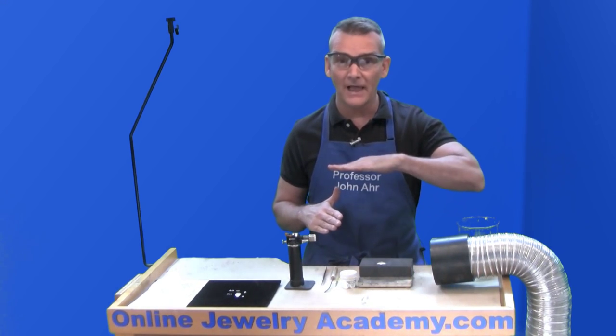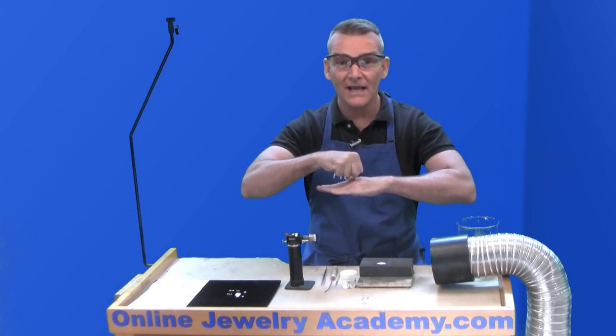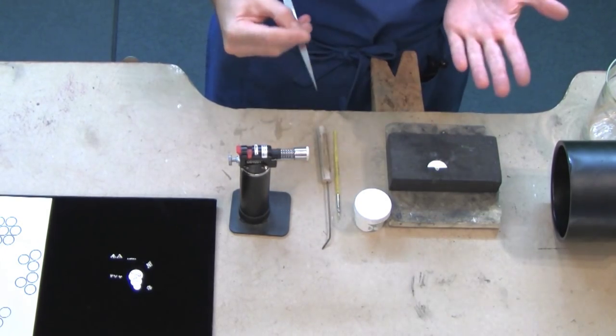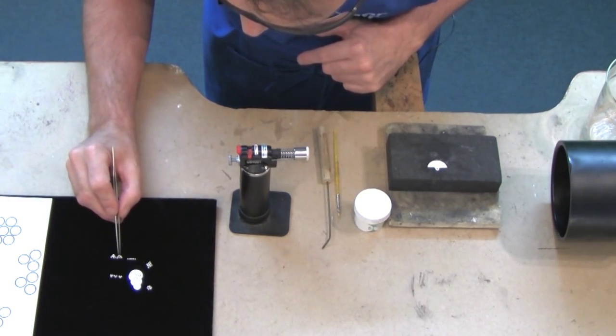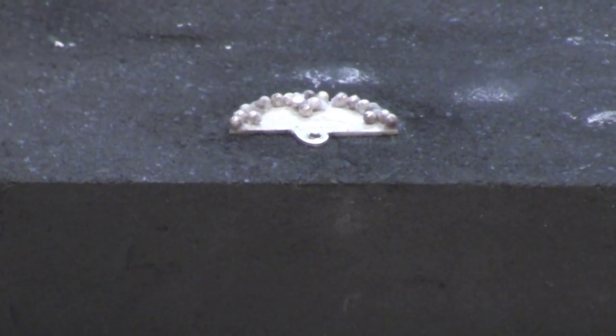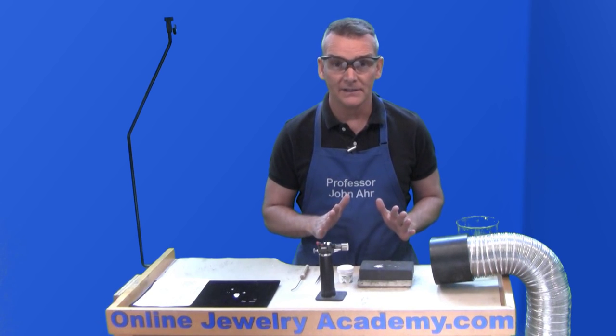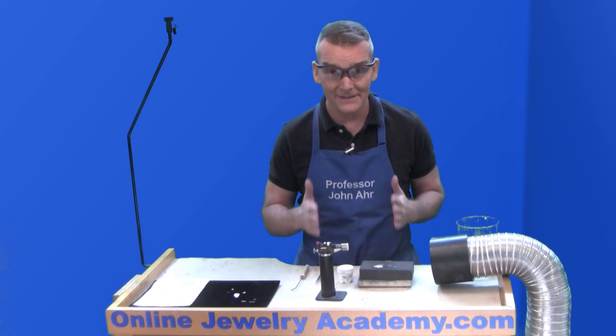The goal is to have a flat surface where there's a ball sitting on top of it that's fused with a tangential connection — meaning it just connects in one spot. I've already pre-painted the flux onto this little piece. Now all I need to do is grab some of the balls and create a pattern. I'm going to start moving them over one by one. I've laid out a lot of balls at one time, which I do to try to avoid fire scale or unnecessary oxidation.